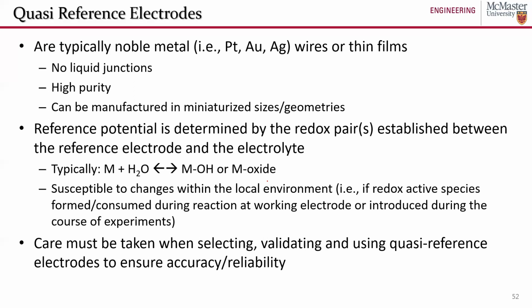A few things to note is that their reference potential is determined by the redox pair that these metals establish with whatever species are present in your electrolyte. Typically this is the metal interacting with the water molecules in your aqueous electrolyte to form either a metal oxide or a metal hydroxide. So it's this metal oxide or metal hydroxide redox pair that defines the electrode potential of your reference electrode. It's not as well defined as a conventional reference electrode, but with enough care and control, you can have an idea of what redox processes are occurring on your reference electrode and dictating its potential.